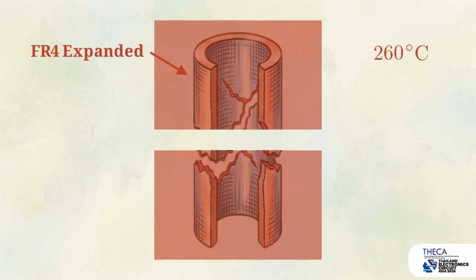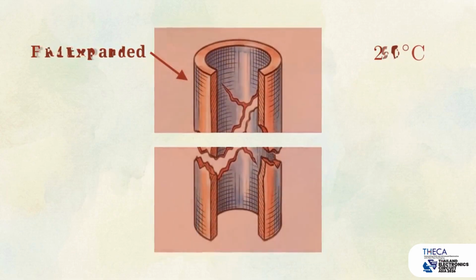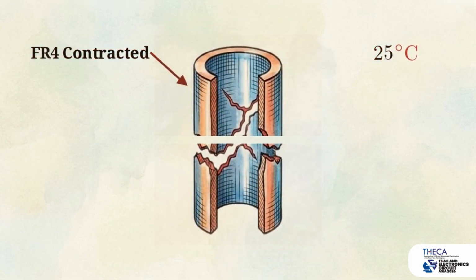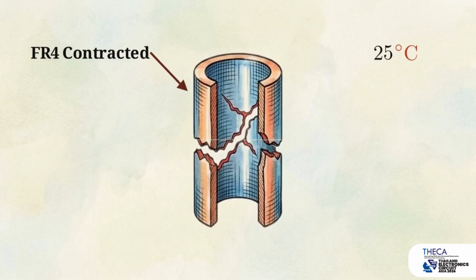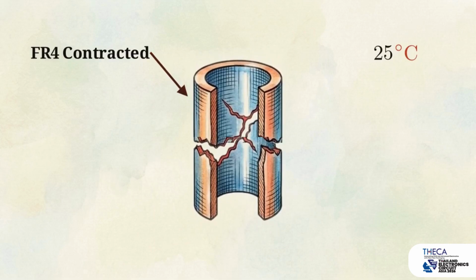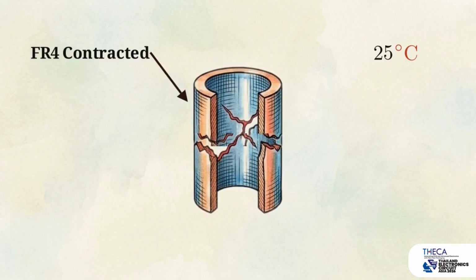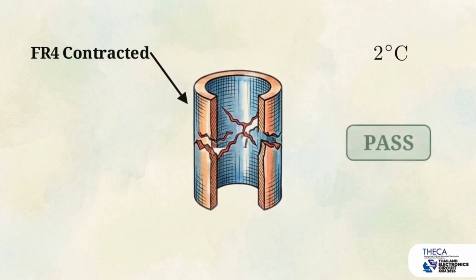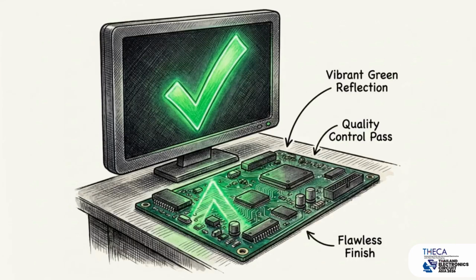As the board exits the reflow oven and returns to ambient factory temperature, a secondary physical reaction occurs. The FR4 cools and contracts to its normal size, pushing the torn faces of the copper back together, re-establishing a physical connection. Because the torn edges are physically touching, current flows perfectly during the final in-circuit test. The automated system registers a green pass. The defect is now physically fatal, but electrically invisible, waiting for a minor heat spike or vibration in the field to separate the faces again.